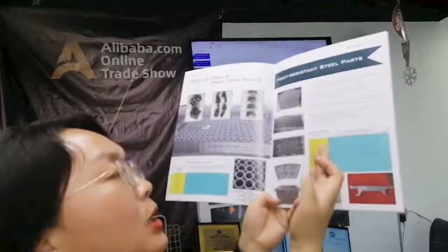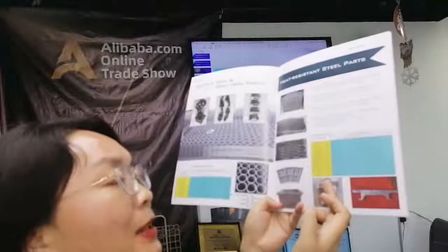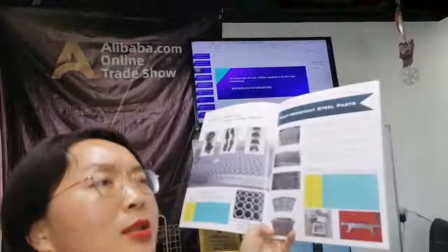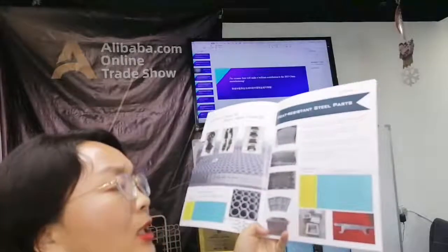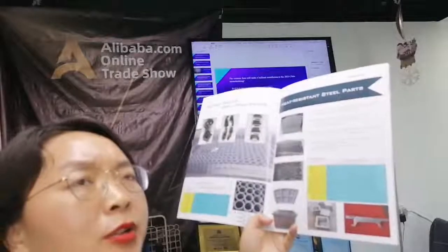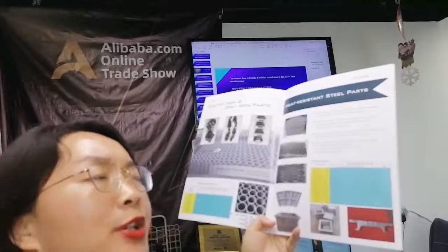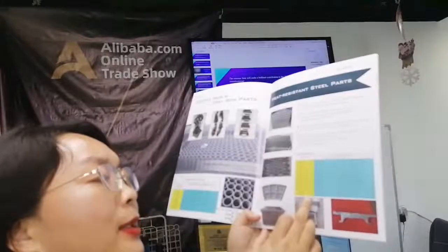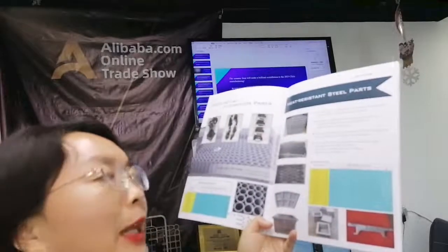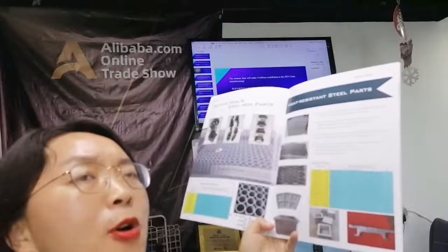For all the steel castings, especially for 2.4879 material, this material can resist about 1,150 centigrade working temperature, but in this working condition, we also require high abrasion resistance. But 2.4879 has very good heat resistant property, but not good wear resistant property.